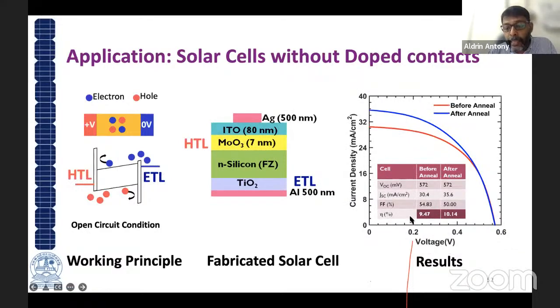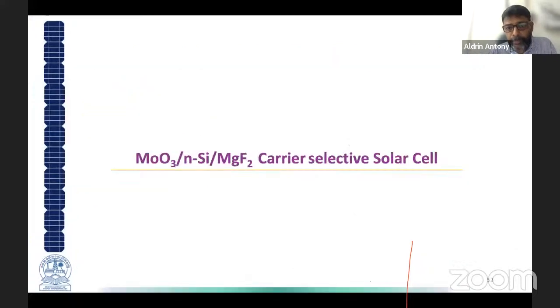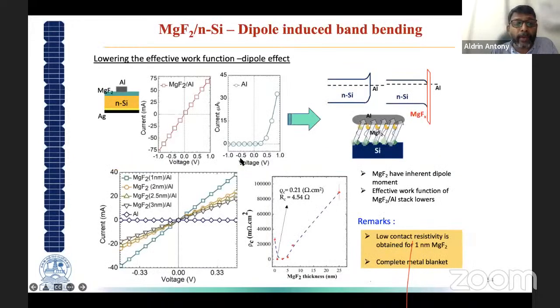And then we anneal the sample. Then we increase the efficiency up to more than 10%. This was the result with a normal, low-cost, dopant-free crystalline silicon solar cell by the carrier selective method. And then we further, rather than titanium dioxide, why not have a fully evaporated thing? So we tried to put magnesium fluoride on the backside. What happens with the magnesium fluoride? When magnesium fluoride comes on the backside of an N-type silicon, that is, when there is only aluminum, it forms a band bending upwards with an N-type silicon.